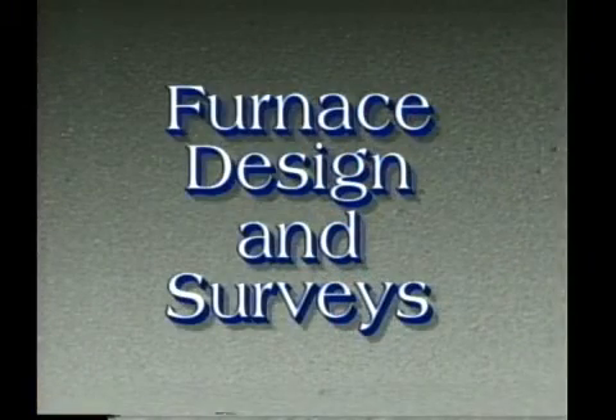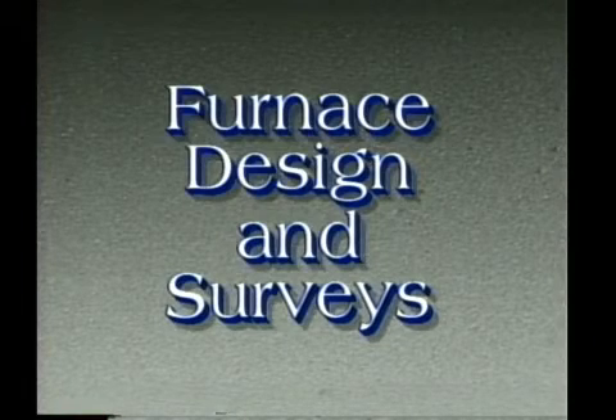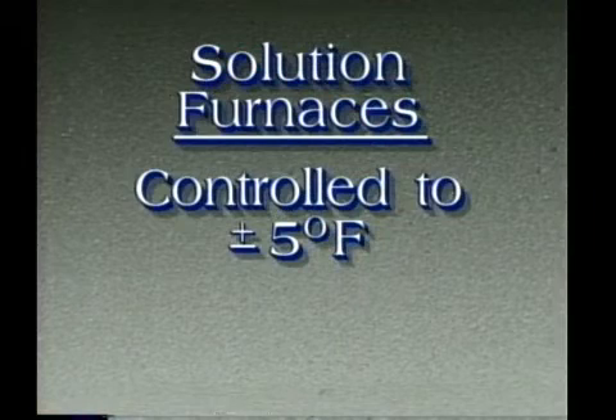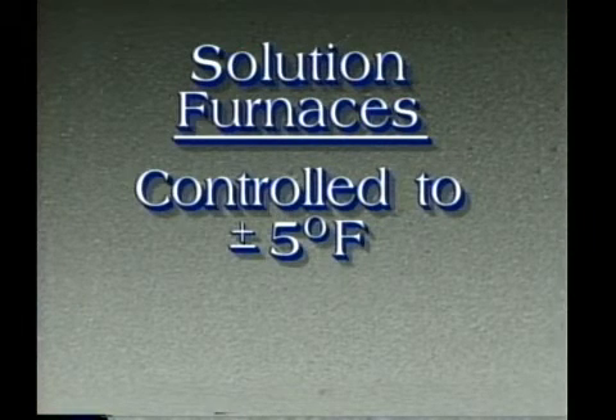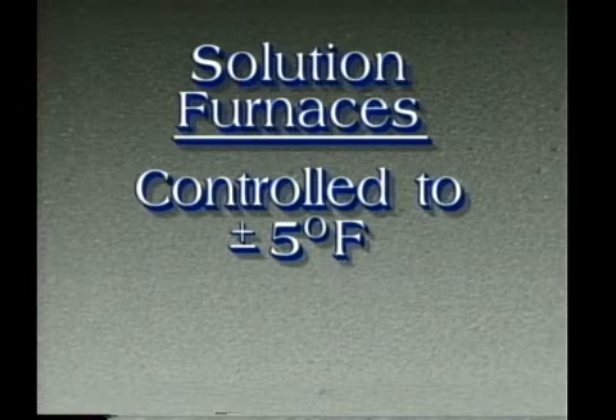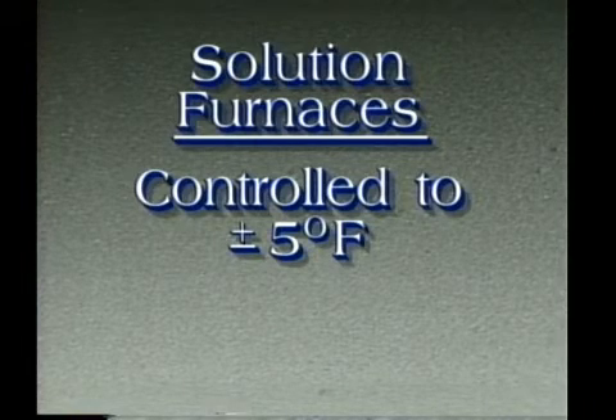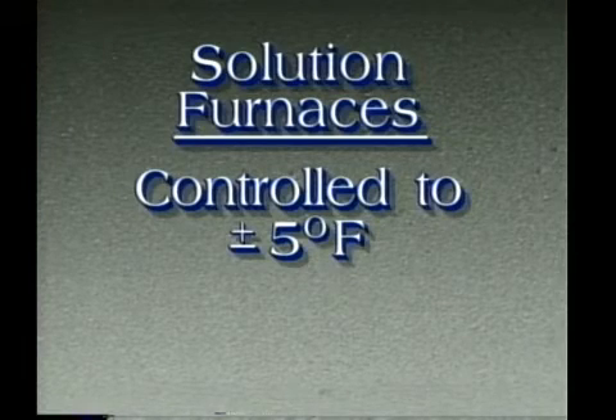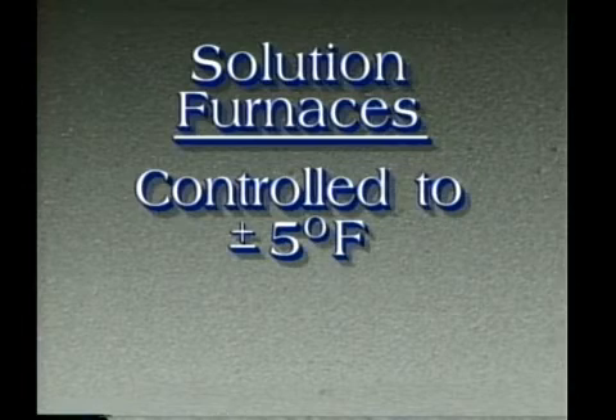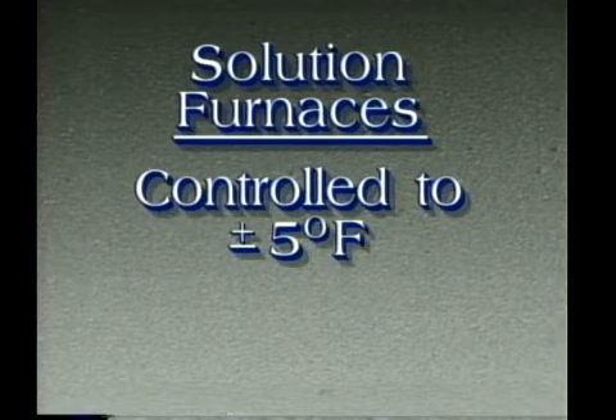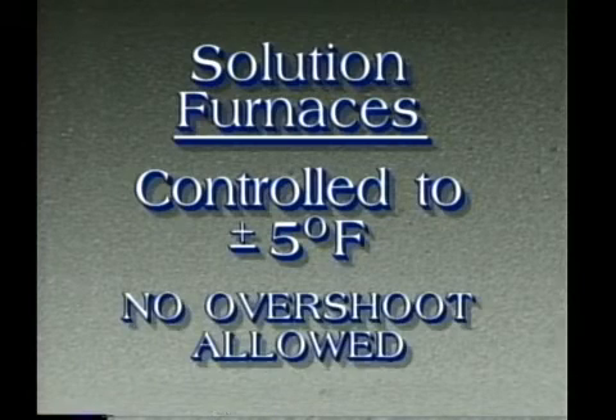Controlling the temperature distribution of a furnace or oven used for solution heat treating and aging aluminum alloys is one of the most critical operations in the plant. Precise temperature control is necessary. Low properties and even permanent damage can be done to parts if the temperature is not adequately controlled. Aluminum solution heat treating furnaces and aging ovens can be very large, and the temperature of the entire work zone must be controlled to as close to plus or minus 5 degrees as possible. The heat treater must have complete assurance that the temperature variation within the whole furnace working zone is maintained within the temperature tolerance required, with no overshoot allowed.